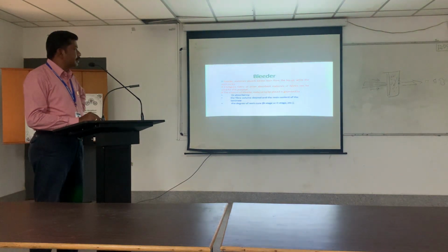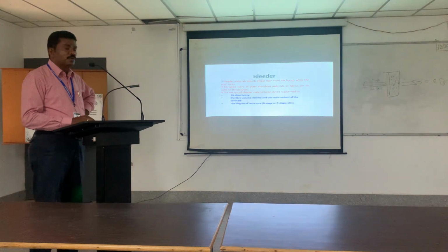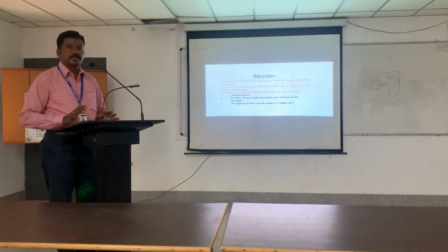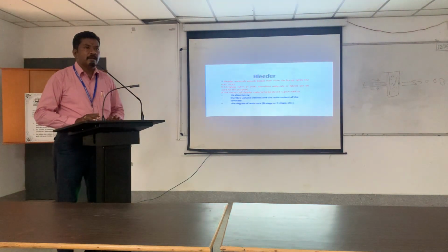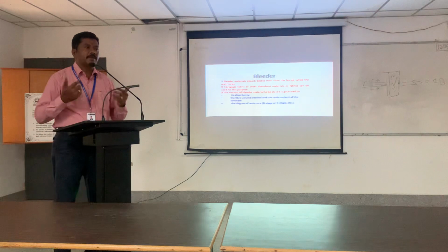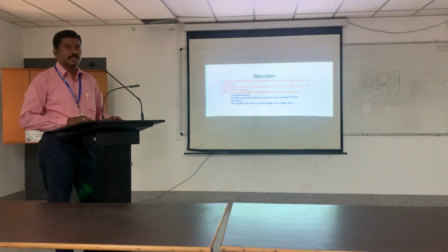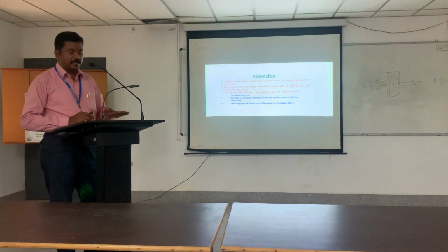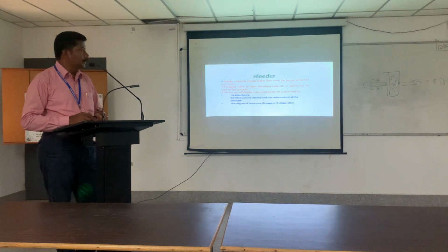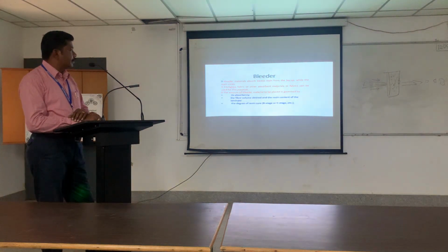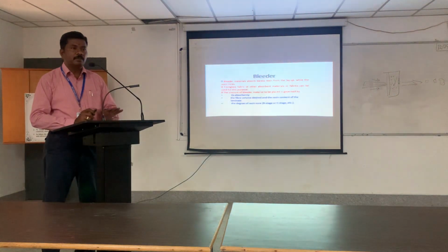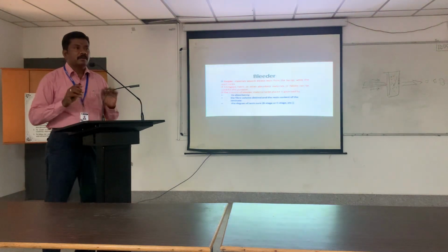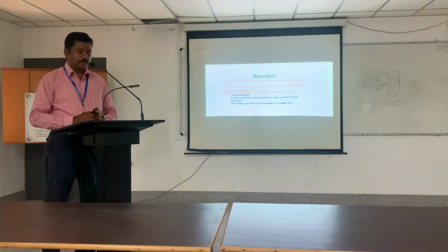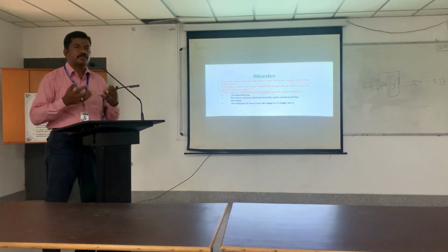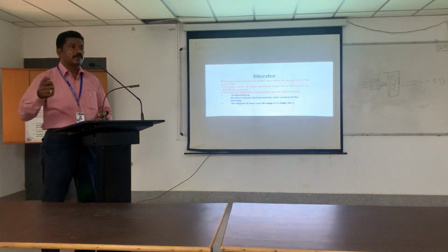The amount of bleeder material to be placed is governed by its absorbency. If you are using 100 ml of matrix material and you put more bleeder material, if it removes all the matrix material, then the bonding will not be good. Okay, so appropriately you have to calculate and that much material should be placed. It depends on its absorbency, the fiber volume, and the resin content of the laminate. How much fiber should be left, how much matrix should be left, accordingly you have to select the bleeder material. If it absorbs all the matrix, then the bonding will not be there.